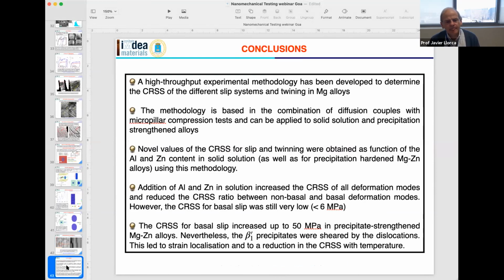So just to end up, I have presented a high throughput experimental methodology to determine the critical resolved shear stress of different slip systems and twinning in magnesium alloys. The methodology is based on the combination of diffusion couples with micropillar compression tests and can be applied to solid solution and precipitation strengthened alloys. Novel values of the critical resolved shear stress for slip and twinning were obtained as a function of aluminum and zinc contained in solid solution, and also for precipitation hardened magnesium-zinc alloys.